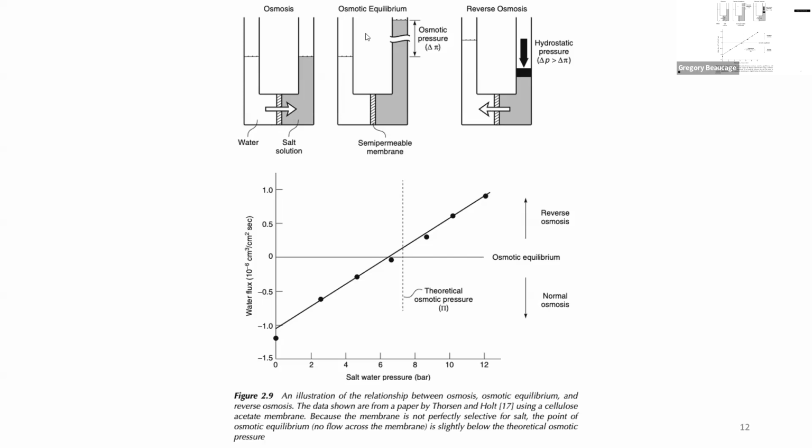You know? Then this is what happens if you want to measure the molecular weight, like an analytic osmotic measurement. So the higher this goes up, usually this pressure is like nRT. So basically, you can get the number of salt particles that went in, and if you know the mass that you shoveled in, you can figure out the molecular weight of each one. If you know how many, and you know the total mass you put in, then you get the molecular weight by the ratio. Right? So that's kind of an analytic technique.